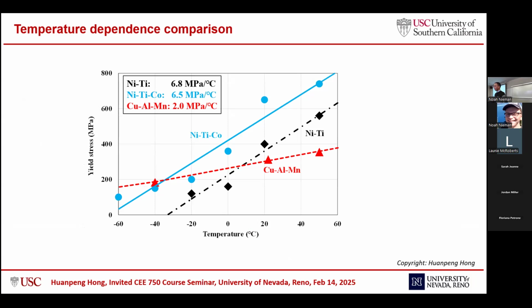So here's a comparison of the three materials. This curve shows the yield stress dependence on the temperature. We used a linear fitting for these three materials. The larger the dependence on temperature, the more sensitive the yield stress is to temperature. For nickel titanium and nickel titanium cobalt, the dependence is around 7 megapascal per Celsius.